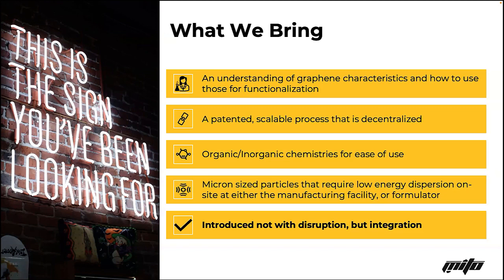Our organic and inorganic chemistries make for ease of use because as it comes out of the process, it is a micron-sized material, which is great for EPA and TSCA, just because they don't want anything below 10 microns, and I don't want to handle anything below 10 microns because standard HEPA equipment can't really handle that on an industrial scale. So we make these micron materials, and as it lets down into the polymer, it goes more submicron. The micron-sized particles require low energy dispersion, so we don't have to do ultrasonication, and it's a very easy mixing solution where we can just go in with a drill and paint mixer and integrate, because everything that we come to the table with is introduced not with disruption, but with integration.